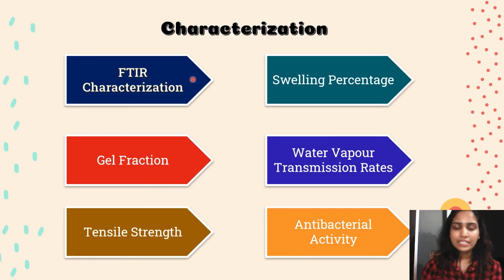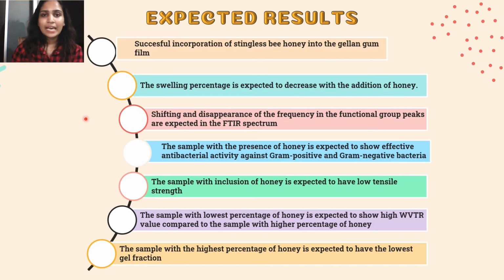The characterization that will be performed is FTIR characterization, swelling percentage, gel fraction, water vapor transmission rates, tensile strength, and antibacterial activity. As for the expected results, I would expect the successful incorporation of stingless bee honey into the Gellan gum film. The swelling percentage is expected to decrease with the addition of honey. Shifting and disappearance of the frequency in the functional group peaks are expected in the FTIR spectrum. The sample with the presence of honey is expected to show effective antibacterial activity against gram-positive and gram-negative bacteria.